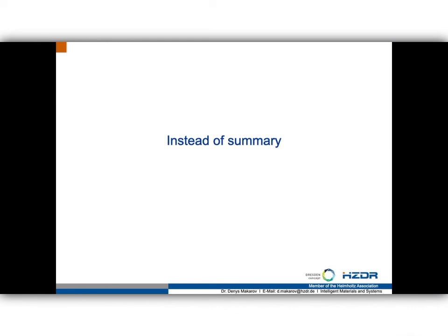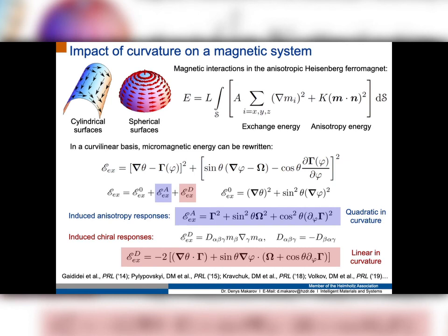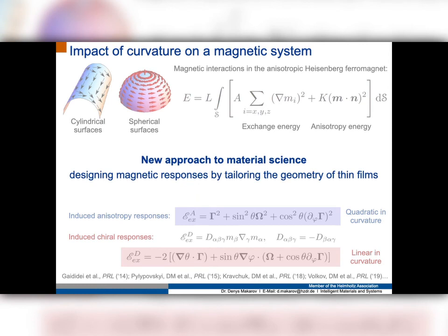All right, instead of a summary, I would like to come back to this slide which I showed at the very beginning, where we analyze the impact of curvature on a magnetic shell, or ferromagnetic shell in this specific case, where you can see that geometry can cause additional anisotropy and chiral responses in the system. In this case, you can tell that you can use curvilinear magnetism as a platform to design chiral and anisotropic magnetic responses in the system by tailoring the geometry of the thin film. And this is simply complementary to the standard material screening approach which we use in the magnetic community to design chiral responses, for example. It's a new approach to material science which you can now start exploring for fundamental investigations, but also for different types of applications such as magnetic field sensors.